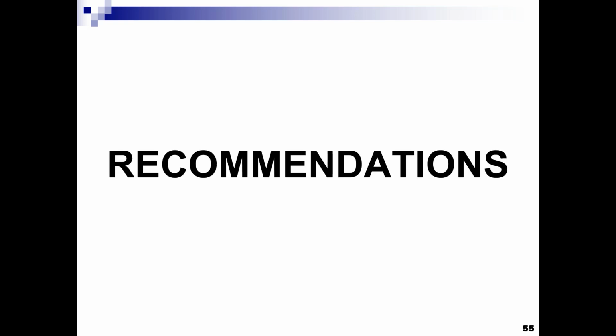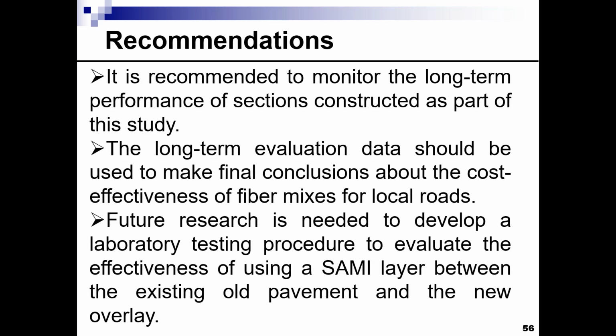So I would like to make the recommendations based on what we have done and on the results that we obtained. We have monitored the performance, but we only monitored it for 6 months. During the first 6 months, we do not expect any difference in the performance of the different test sections, unless there is a premature failure, and we made sure that there was nothing there. Therefore, the long-term performance should be evaluated.